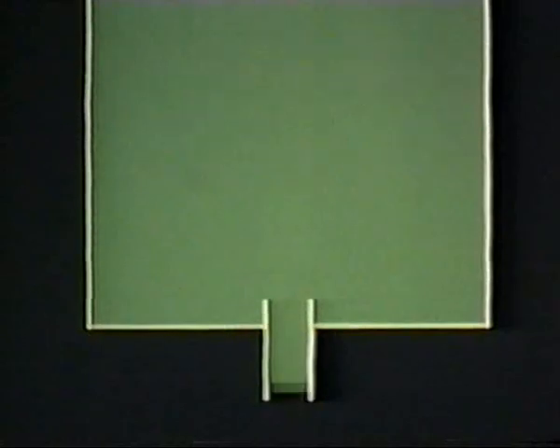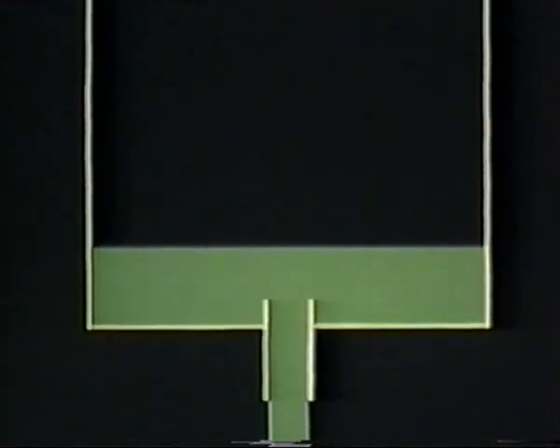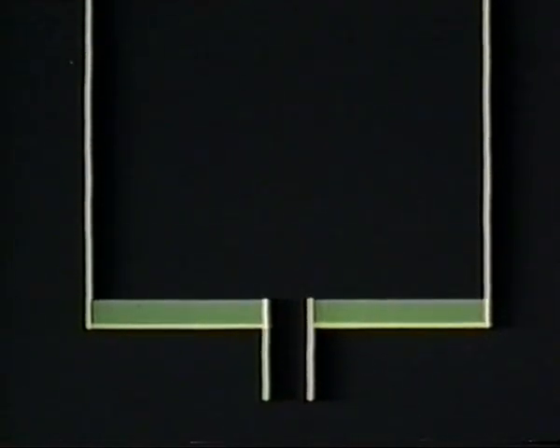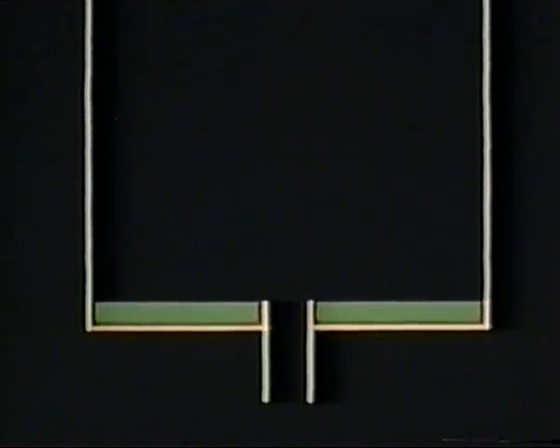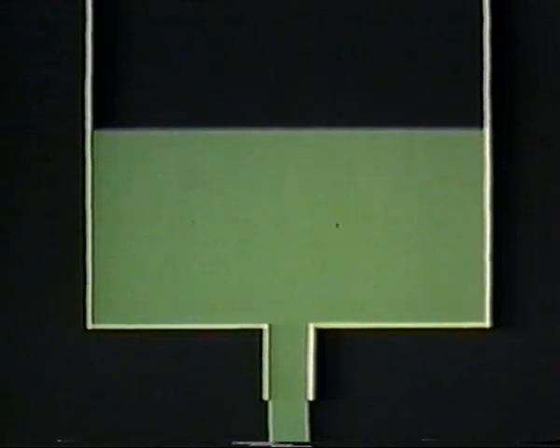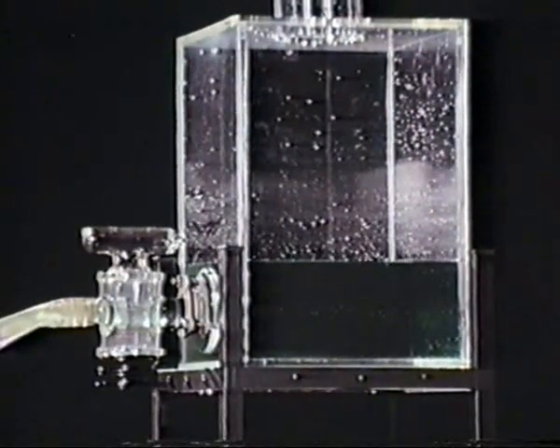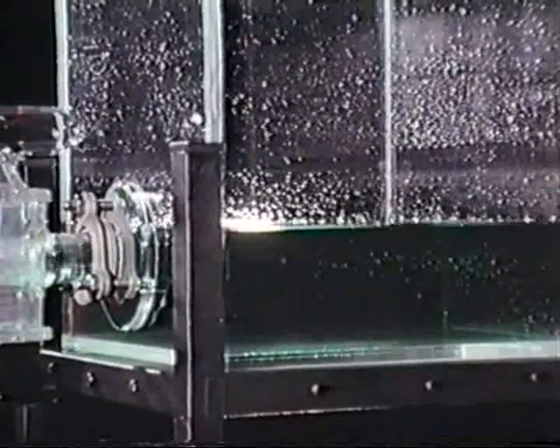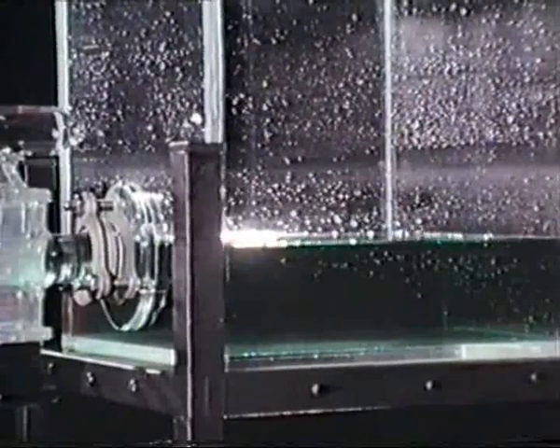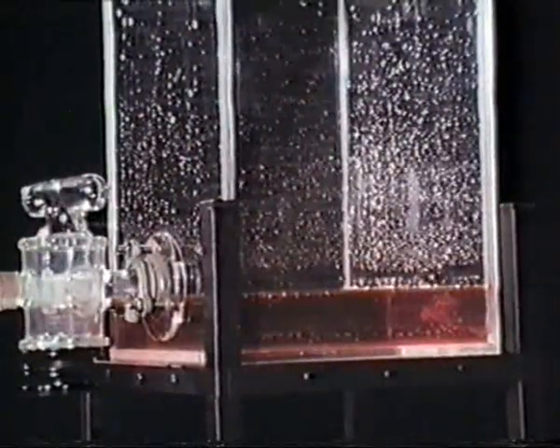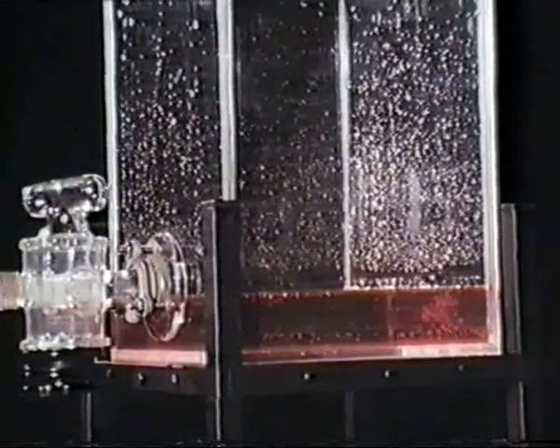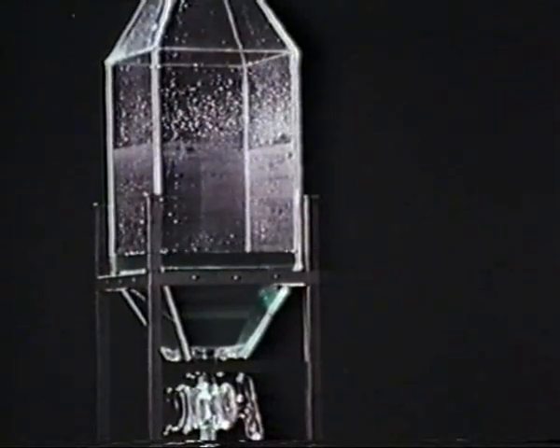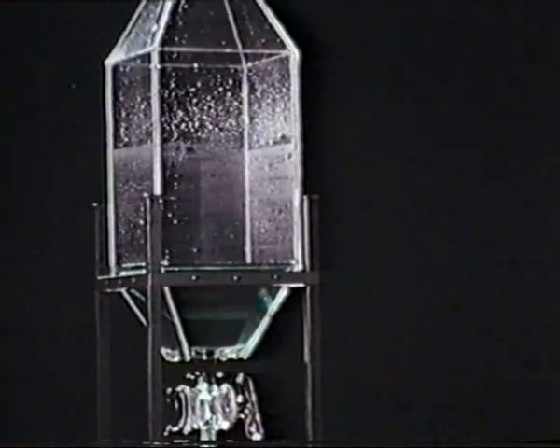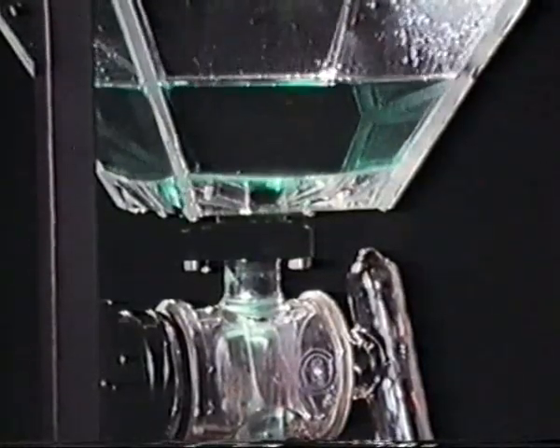In the prevention of corrosion, a first consideration should be the effects of shape, as for example, on drainage in storage vessels. If an outlet pipe is above the bottom of the tank, residual liquid may in time become more concentrated and corrode the interior. Complete drainage is achieved by correct choice of shape in the design. Different outlet faults are commonly found. With incomplete drainage, many liquids may concentrate from evaporation and become more corrosive. However, some liquids become dilute when left in a nearly empty tank. Sulfuric acid, when concentrated, does not attack iron, but becomes aggressive when diluted. Complete drainage will avoid corrosion.